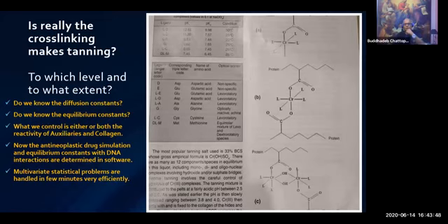But where actually it happens, I have my own doubt. Whether it happens in the triple helix, between the fibers, or between the fiber bundles. I have seen in a SEM, scanning electron microscopy, of chrome-tanned collagen the cross striation. This cross striation is seen in collagen also. But in collagen, we know it is because of the quarter staggering of the collagen triple helix, which gives the alternating dark bands and light bands.